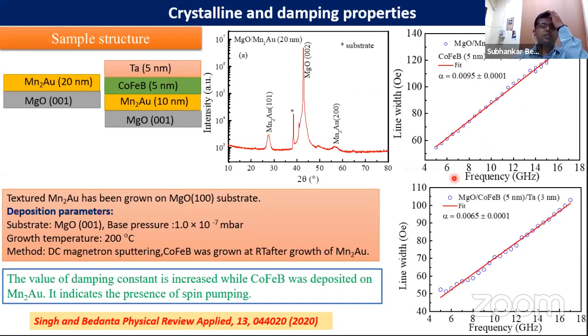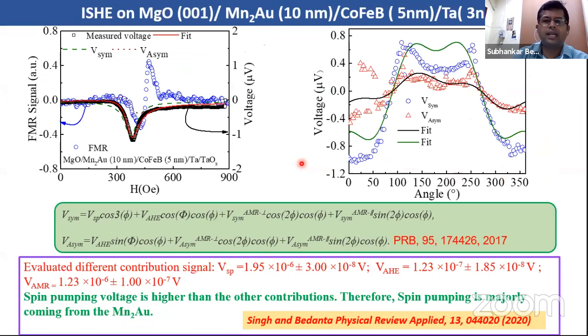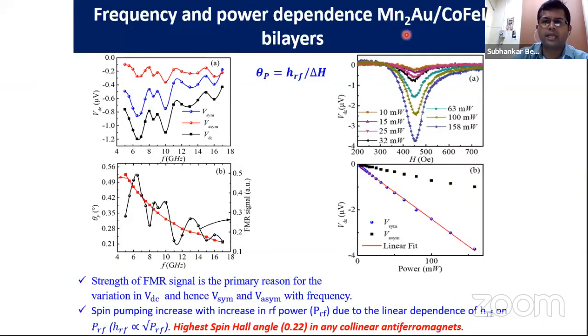But we focused more on the spin Hall effect, which was not done. And we took again the manganese gold. This is an antiferromagnet, cobalt iron boron is the ferromagnet, and we grew the manganese gold nicely by sputtering, and we found that it is indeed giving a very high amount of spin pumping. By doing a similar analysis to what I showed earlier, by fitting these functions for symmetric and asymmetric components, you can disentangle the spin pumping voltage, the anomalous voltage, and so on. We find the spin pumping voltage is larger, and you can indeed calculate the spin Hall angle of this manganese gold. And we have shown the highest spin Hall angle in any collinear antiferromagnet, because usually for collinear antiferromagnets like iridium manganese, nickel manganese, the spin Hall angle is like 0.02 to 0.01 or something like that.